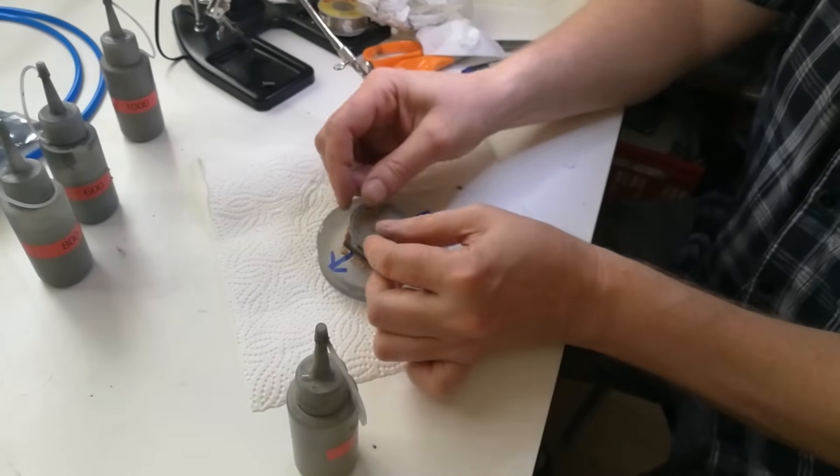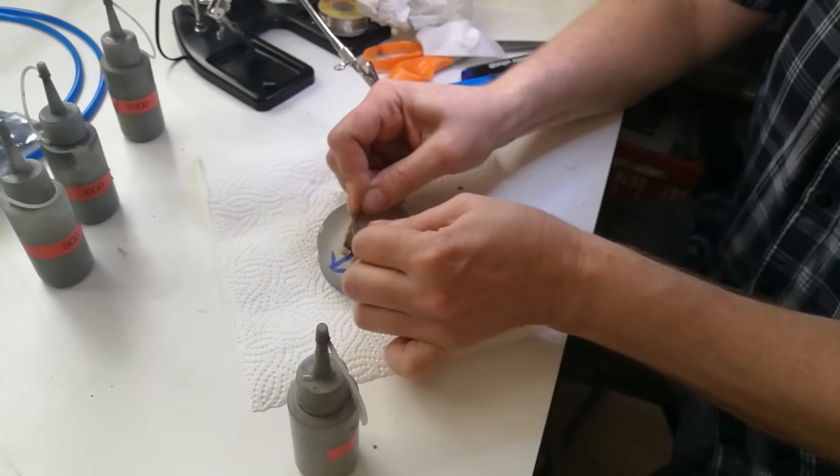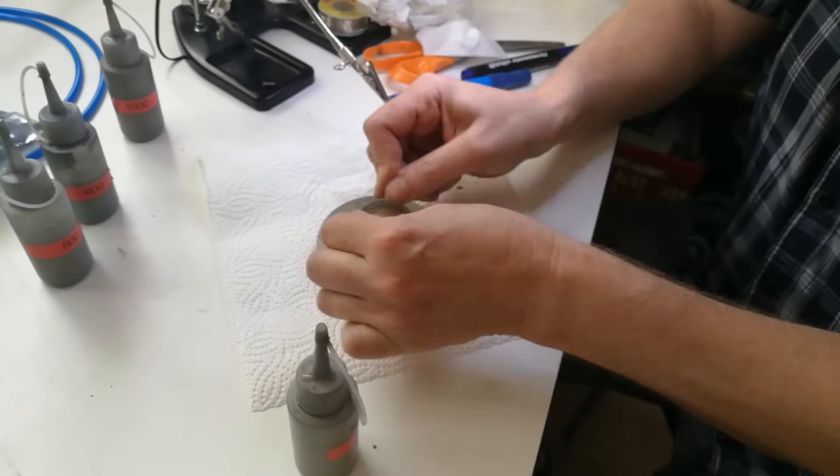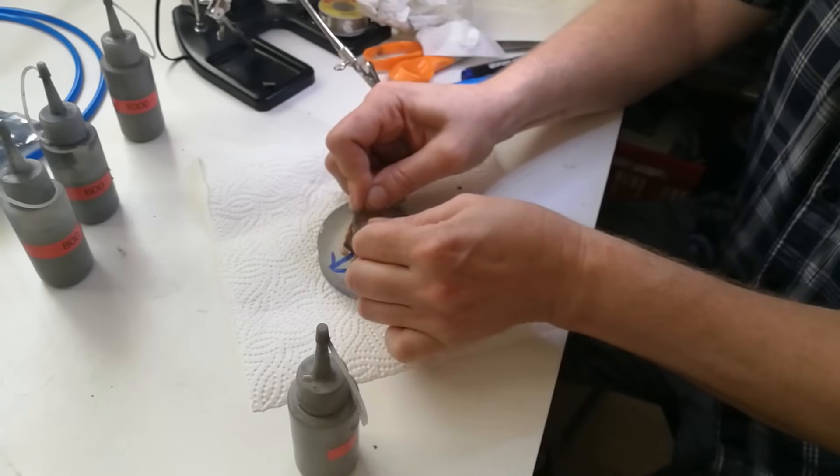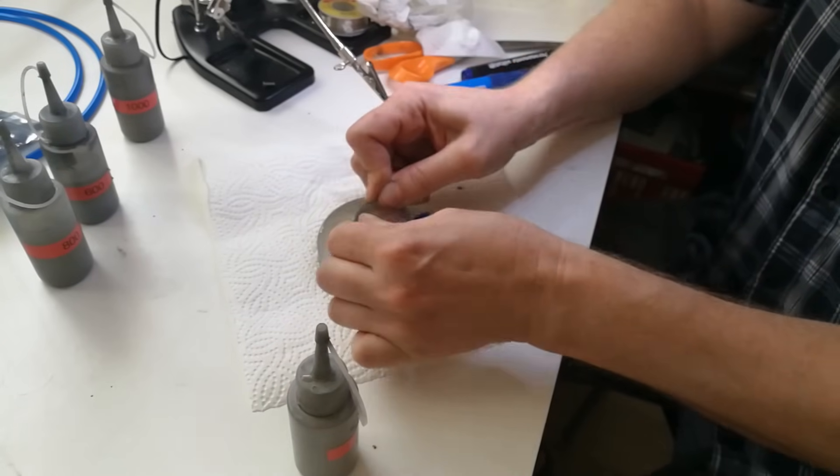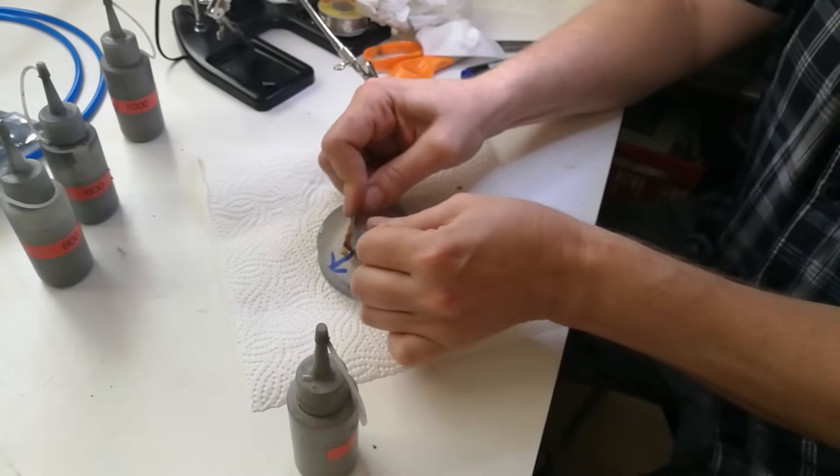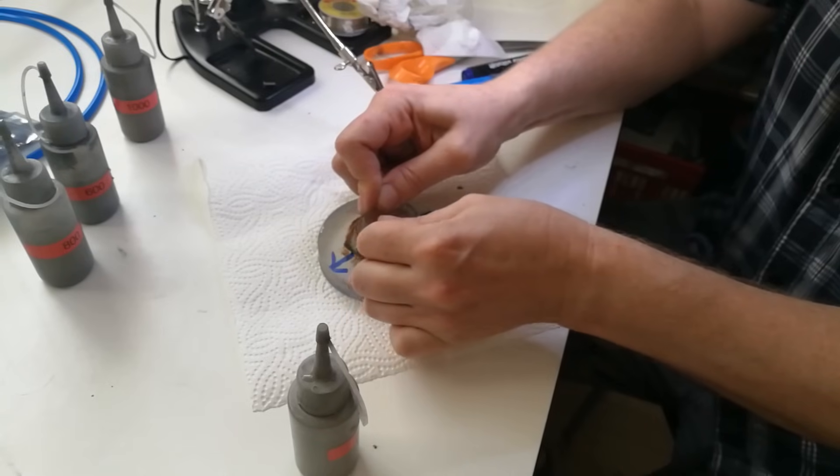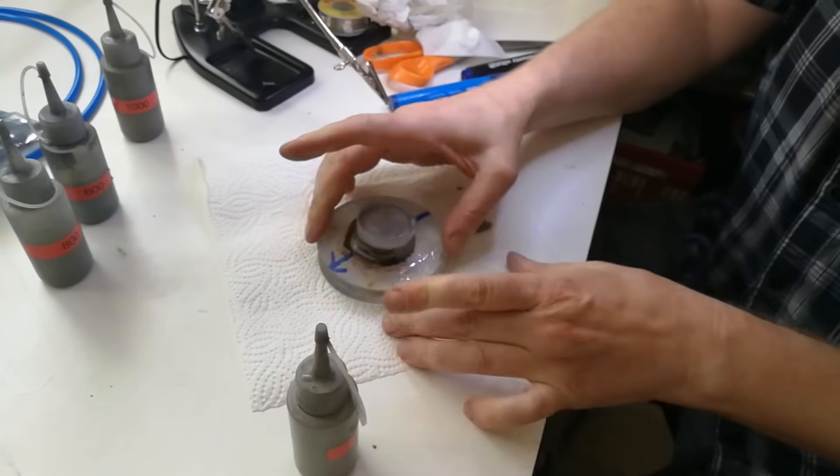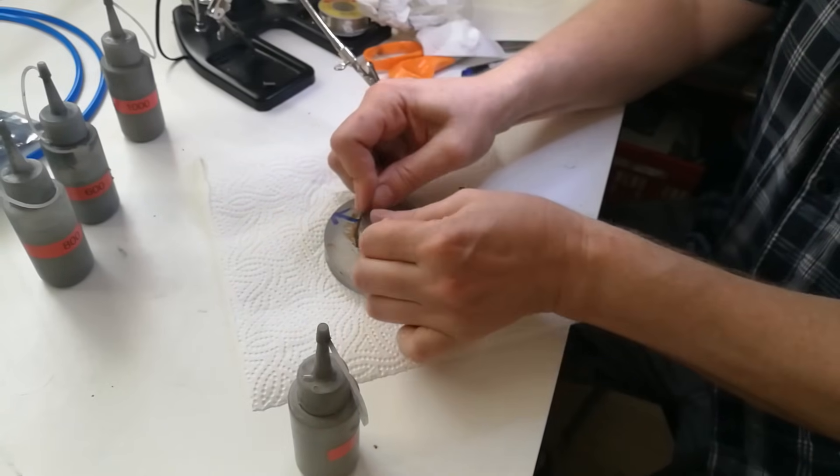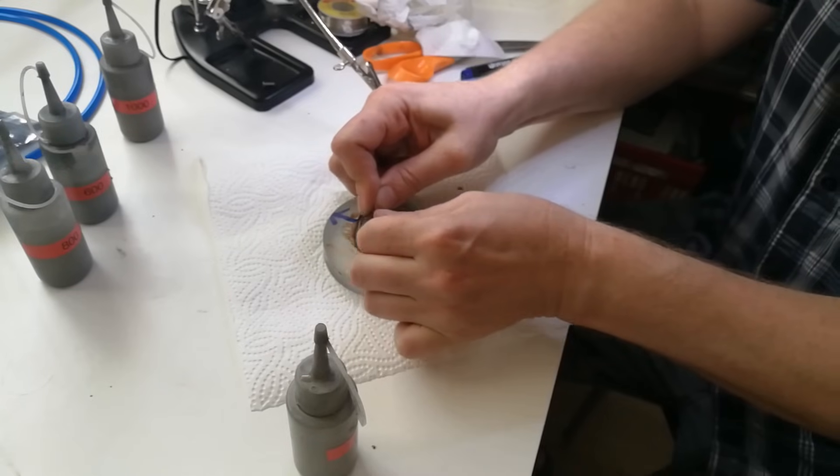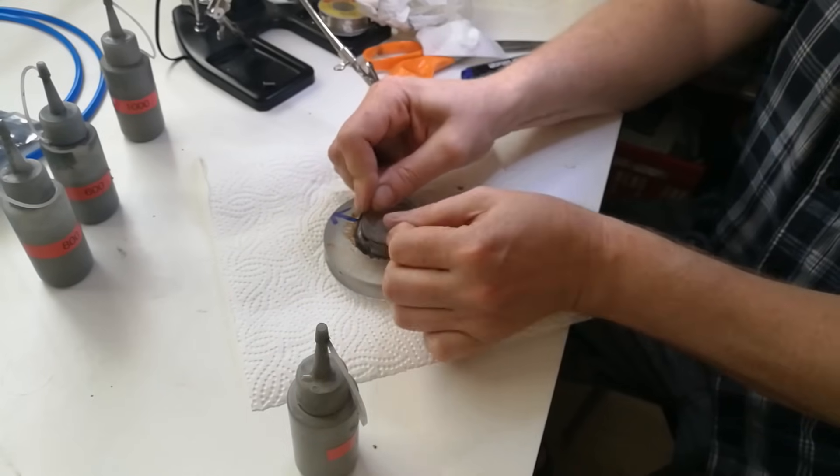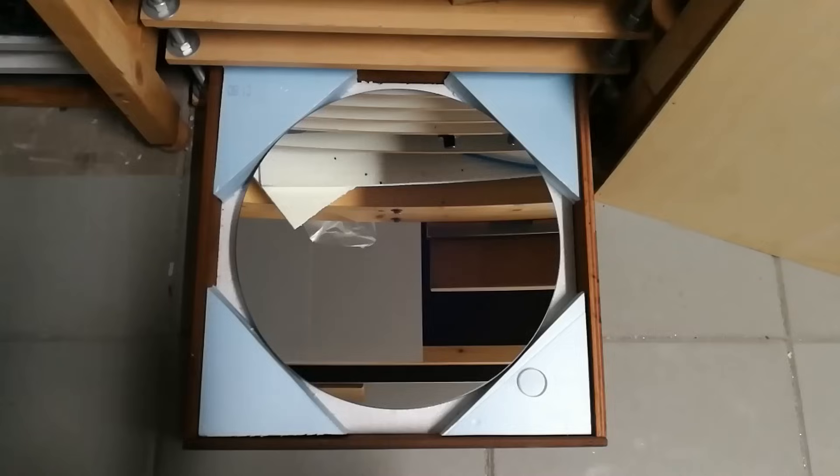Now, as the general time for each grain, for a small blank like this, the time can be actually fairly limited, let's say between 5 and 10 minutes for each grain, apart from the first one. However, this time is mainly dependent on the size of the blank and the pressure that is exerted during grinding.